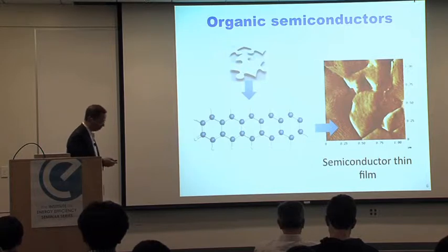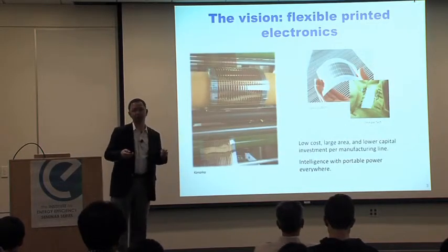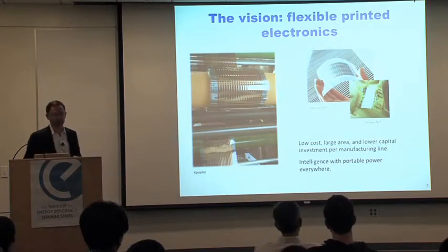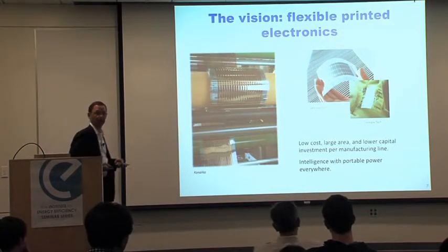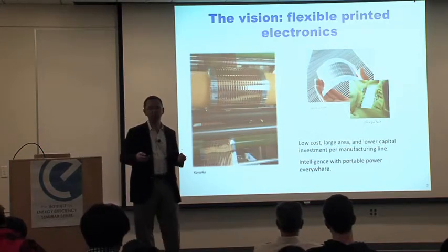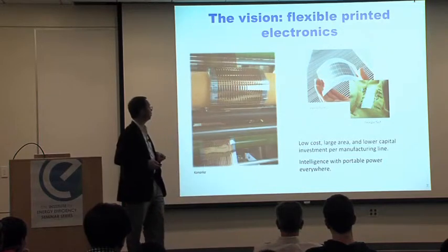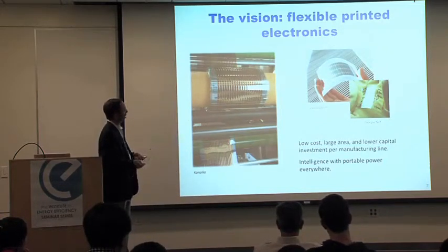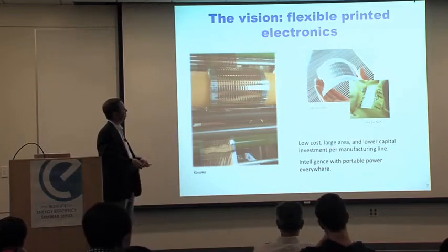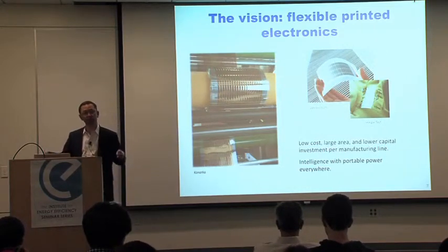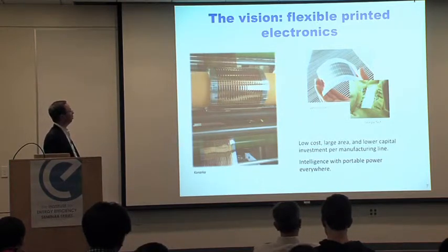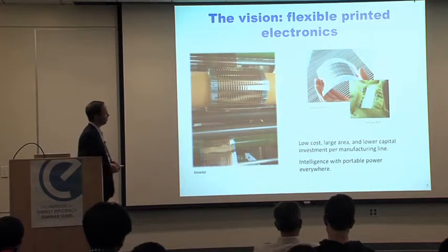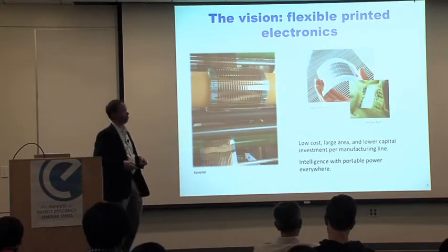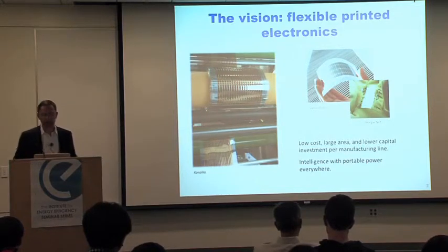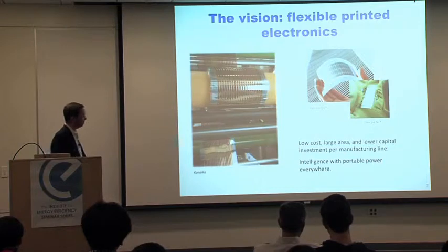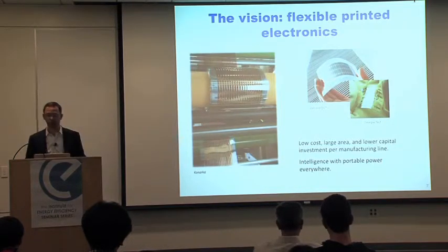And so what you gain also, because you do that low temperature processing, is that your films can be deposited onto substrates, including substrates that usually wouldn't withstand these high temperatures that are used to grow other materials. And so you can envision, this is kind of the vision, of having flexible printed electronic devices with various functionalities at relatively low cost over a large area, and using equipment for the manufacturing of these devices which requires much lower capital investment. And so that's kind of the dream and the goal here for these materials.